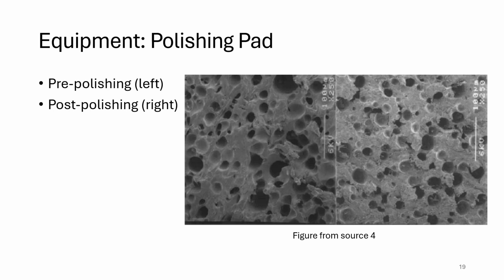Here's an example under a scanning electron micrograph showing exactly what the pad looks like both before and after conditioning, which is a process we will touch on shortly. Something to take note of is the size variation of the holes in the pad before and after conditioning. Not understanding how the pad wears can lead to higher defect rates and a lower process yield.